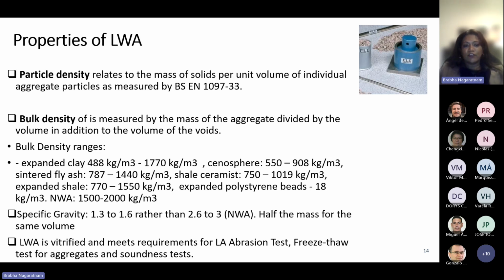So the bulk density has a very high range. So for expanded clay, cenosphere, sintered fly ash, shale ceramics, all the bulk density varies. And like I said, it depends on the size, it depends on the source of the materials. Similarly, with specific gravity as well, usually for most types of lightweight aggregates, it's between 1.3 to 1.6. Now, if I compare that to normal weight aggregate, that's around 2.6 to 3. So that's half the mass for the same volume of aggregate.